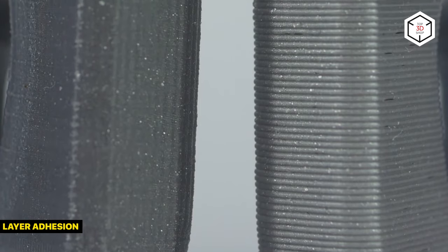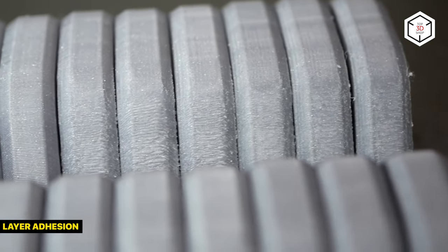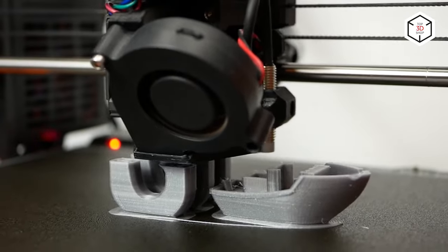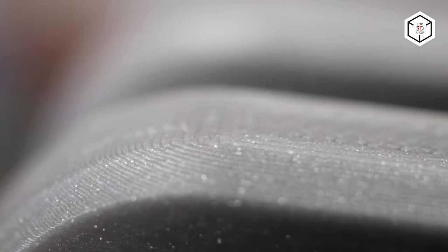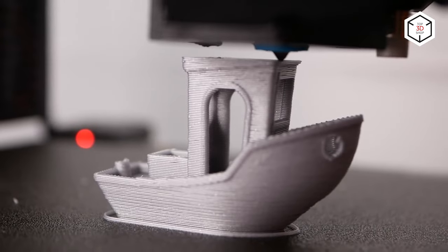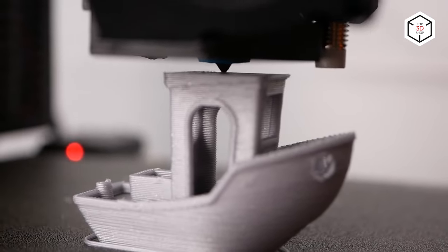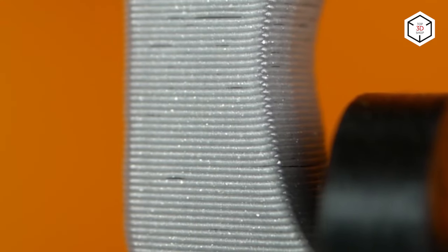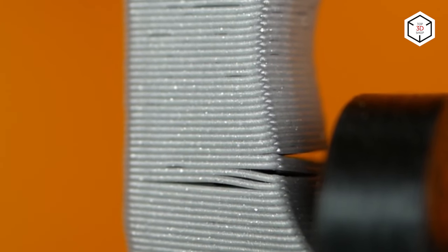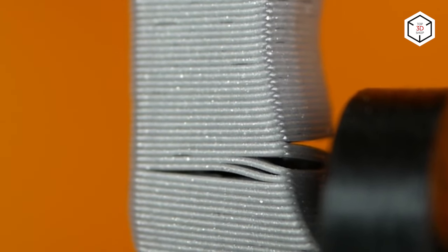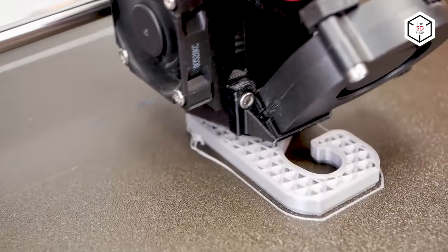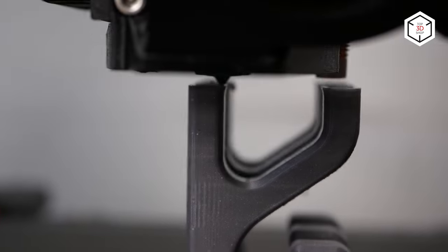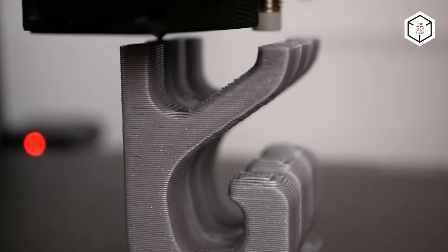Layer adhesion is crucial for FDM-produced parts as their quality depends on the adhesion between the deposited levels. It relates to the binding strength of multiple material layers caused by high temperature and pressure applied to the melted filament. It's important to remember that this strength will always be inferior to the material's own strength. This contributes to the anisotropic nature of the FDM-printed parts. Moreover, a slight deformation while pressing filament to the previous layers results in a wavy surface and visible lines that can still be seen even by the smallest layer height setting. This is why such printouts usually require post-processing.